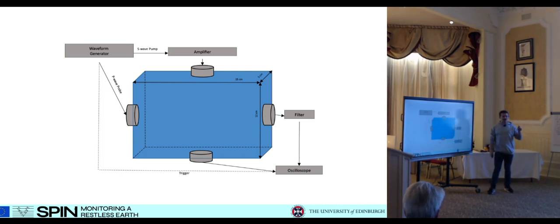We then delay the time of the P wave so that it intersects the S wave at different phases. And we can sample what is the delay time caused by that P wave as it interacts with the S wave. For those of you who are familiar with DAET, the dynamic acousto-elastic testing, which I think was brought up yesterday, it's kind of the same idea.